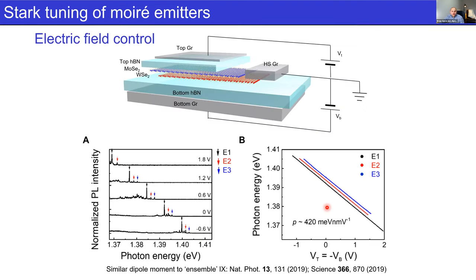Further, because we have this nice device where we can independently control the electric field and the doping, we can apply electric field, and really, because we have this huge permanent dipole, we can tune these across a huge range in energy. So in this case, we tune about 40 millielectron volts, which at least to my knowledge is the largest tunability using the Stark effect of a quantum emitter. So that's quite nice, and again confirms the interlayer nature of these trapped excitons.